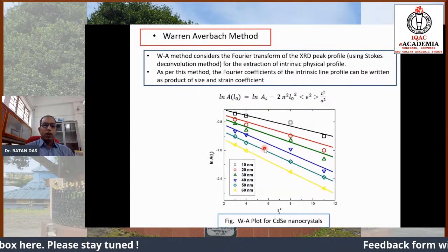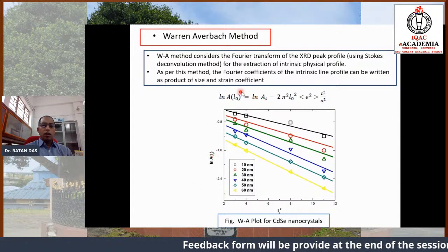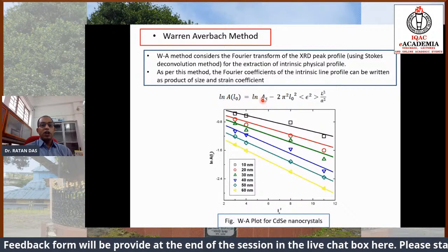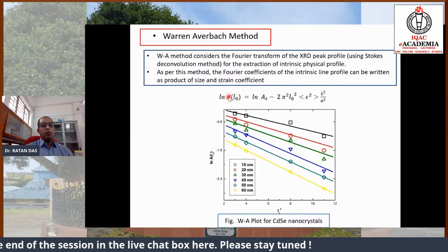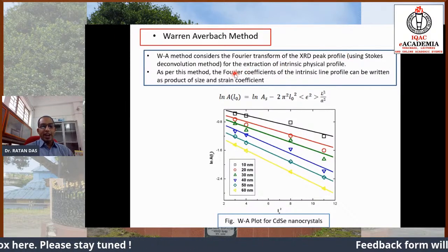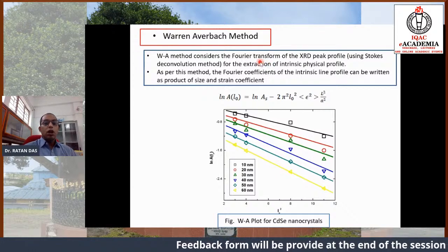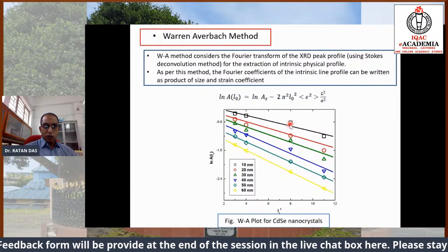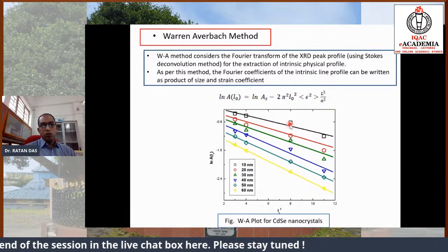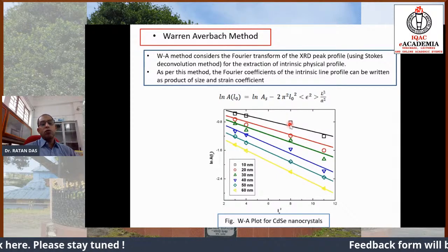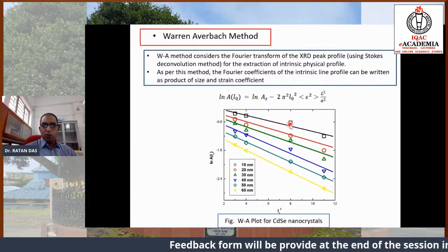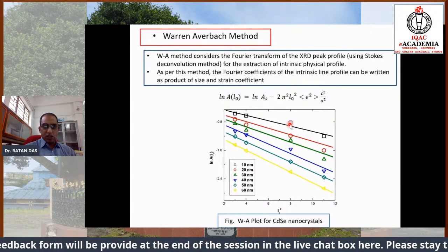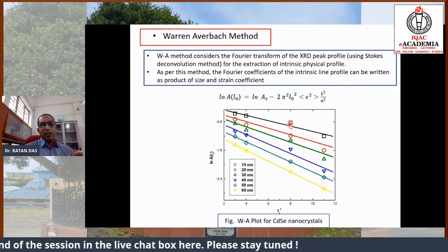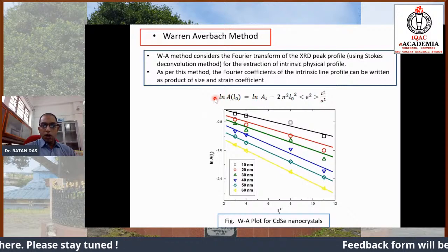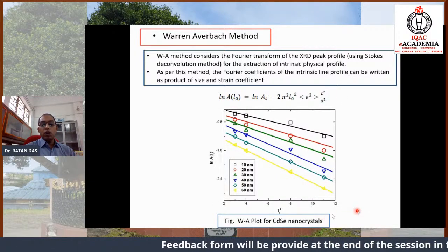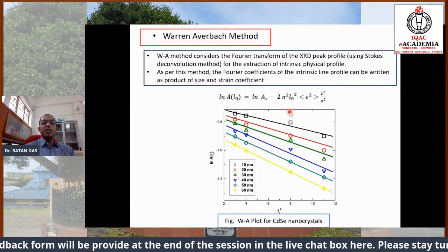Now, I don't want to go into the details, but what I want to tell you is that A_L, A_L0 or A, these are the Fourier coefficients that we can obtain from the Fourier transform of the X-ray diffraction profile after extracting the pattern actually. So we fit the X-ray diffraction pattern either with a Gaussian function, or a Lorentzian function, or a Voigt function, whichever function matches your diffraction pattern well, that function must be Fourier transformed, and from the Fourier coefficient we analyze, or plot, that particular Fourier coefficient where L0 is the column length actually. That needs to be discussed again, because